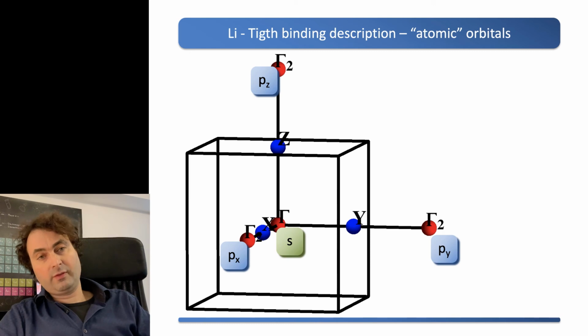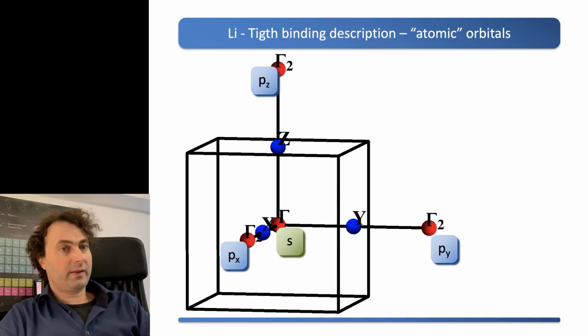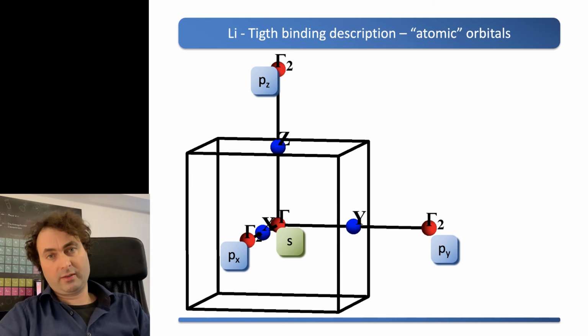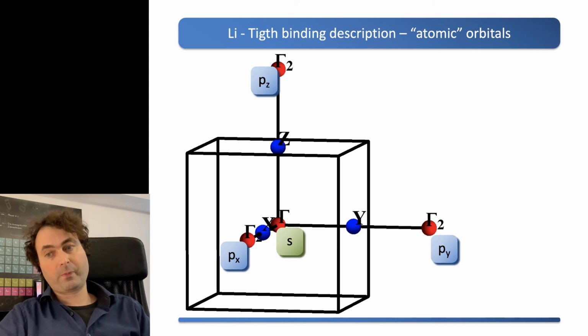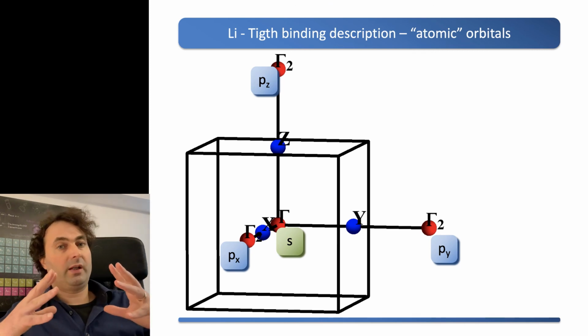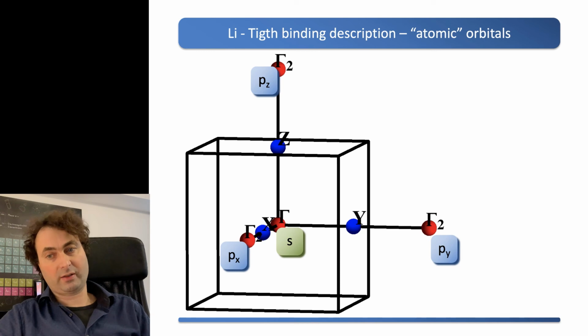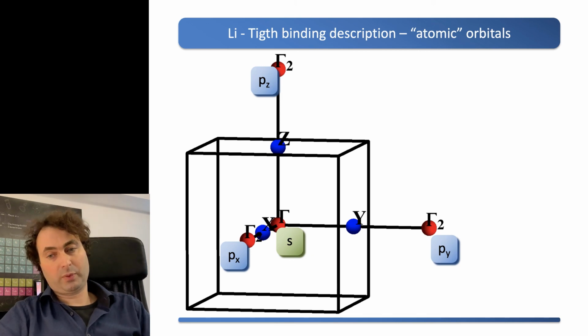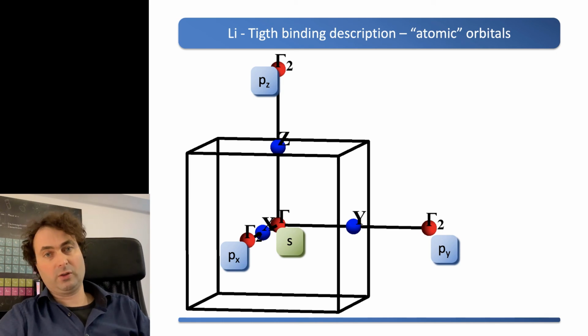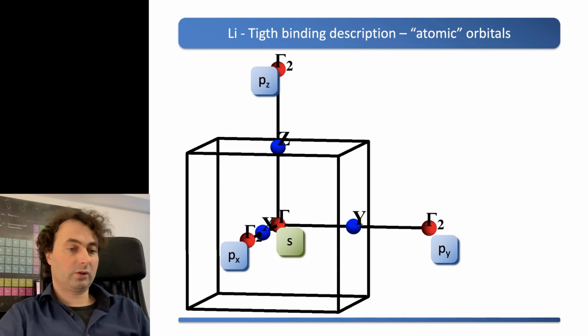And the reason that we can neglect Coulomb repulsion is not so much that the interaction is small, but much more that there is no phase space to which you can scatter. If all states up to the Fermi energy are filled, then you can only scatter electrons from below the Fermi energy to above the Fermi energy, and there's always a gap or an amount of energy associated with this, unless you're perfectly at the Fermi surface, but that's only a very small amount of electrons compared to the total number of electrons.